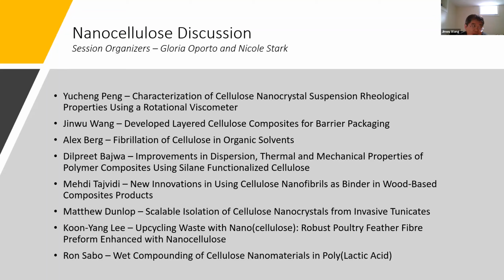In my case, I mainly work with Professor Doug Gardner. We have a project with Flamifa. We try to laminate cellulose with polymers like PP and PE, with different layers. The point is the cellulose has a good oxygen barrier, but not a water vapor barrier. Polymers have a good water vapor barrier, but not an oxygen barrier. So if we laminate these together, we can possibly create a material with both a good water vapor barrier and a good oxygen barrier. So this is one area.